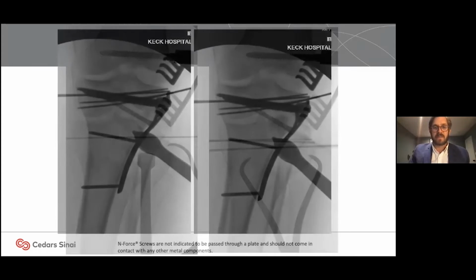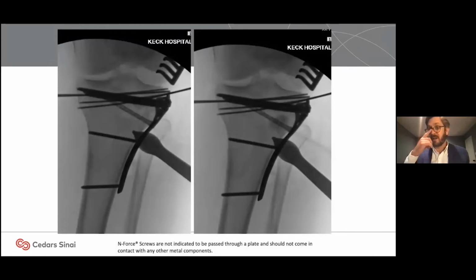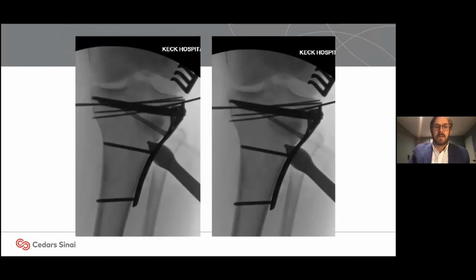In this case, I chose to use a fenestrated screw to deliver a calcium phosphate bone putty. It can be placed through the defect and deliver the calcium phosphate exactly where you want it. I find this to be fairly easy to use and has had good results.